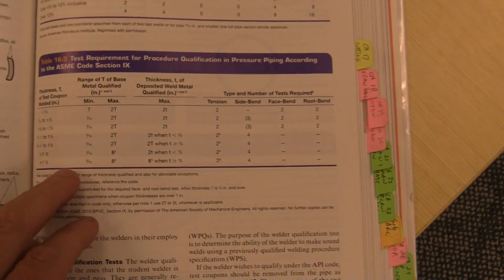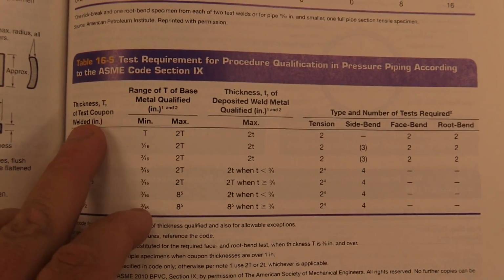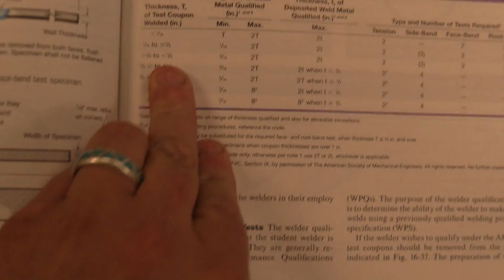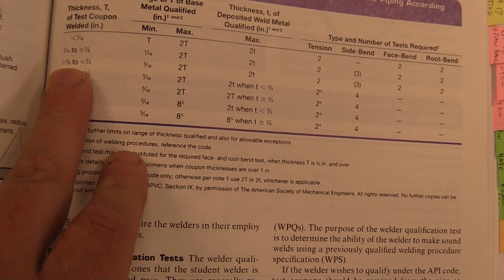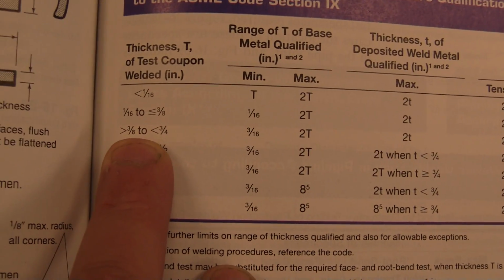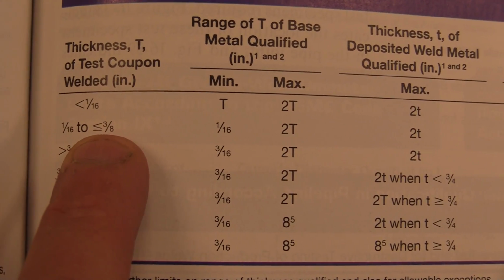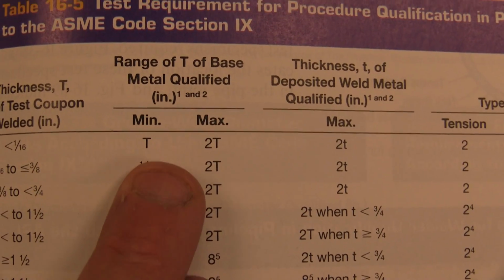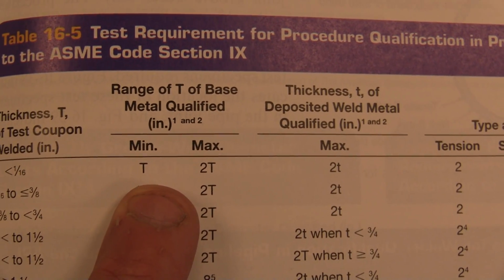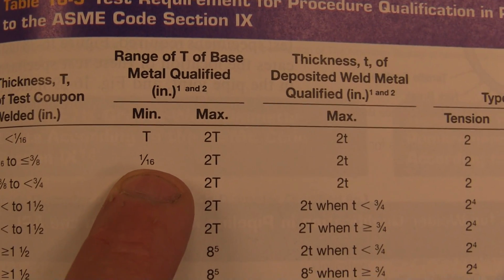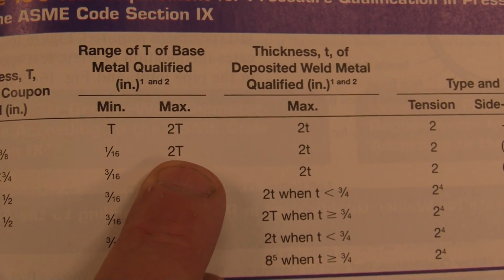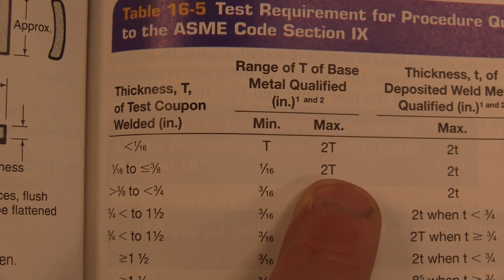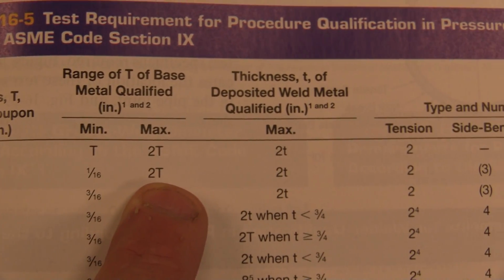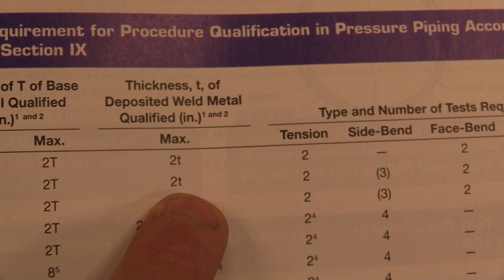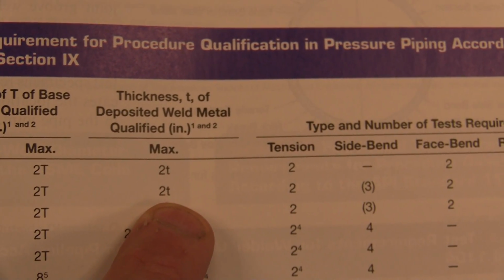So just so that we're clear on a few things. We're going to look at ASME Section 9 right here, okay? So here's the thickness of the test coupon. What we're doing in the shop is 3/8 of an inch, so we're less than or equal to 3/8 of an inch. The range of thickness of base metal qualified, 1/16 minimum. The max is 2 times the thickness, so if you pass at 3/8, you're qualified to 3/4. The thickness of the deposited weld metal is 2 times the thickness. Okay.